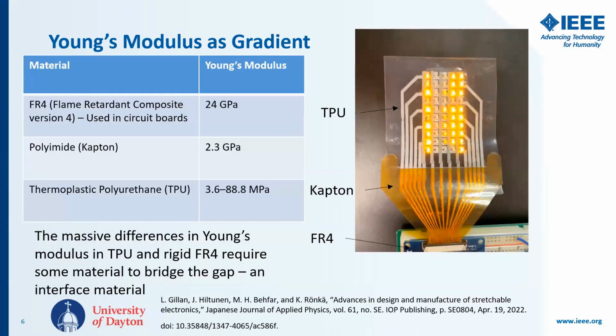Directly connecting a soft substrate to a hard one, such as TPU to traditional FR4 circuit board material, can cause many issues. First of all, there's a massive change in the Young's modulus going from the hard substrate to the soft substrate. That means when the sample is strained, the most likely failure point is actually at the junction between hard and soft. This interface between these two materials causes issues.